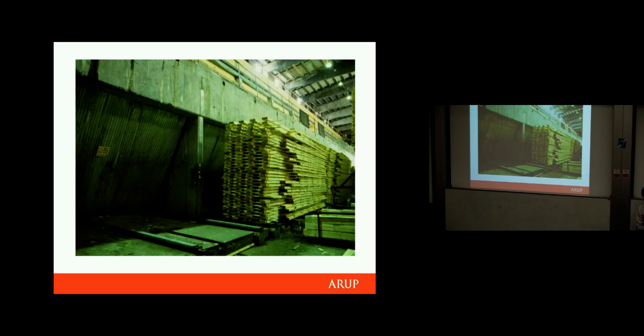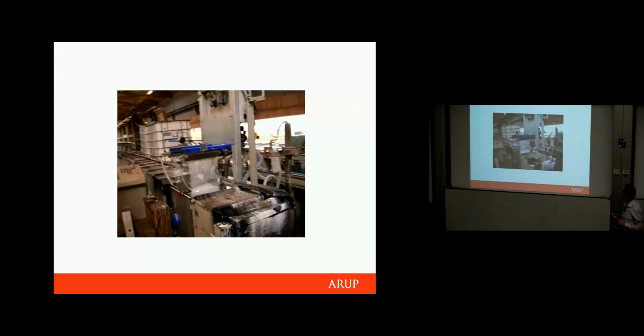And the other nice thing about drying out the wood is that you probably know that green wood is quite wet. As it dries down, it shrinks. But by drying it down in the kiln, all that shrinkage is happening in the factory before we make the glulam beam. So if we're building buildings, it's much easier to work with something which is going to be fairly stable. We can build in green oak, or any other green timber, but we're going to have to detail around all that shrinkage. So if we can make the shrinkage happen in the factory, in the kiln first,